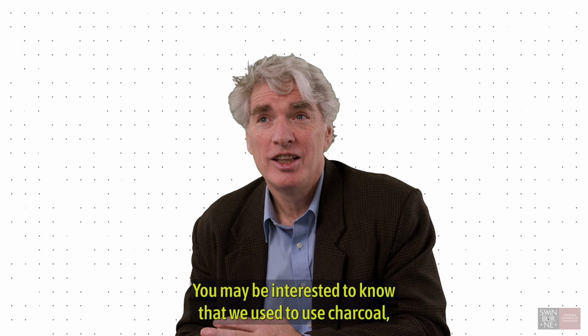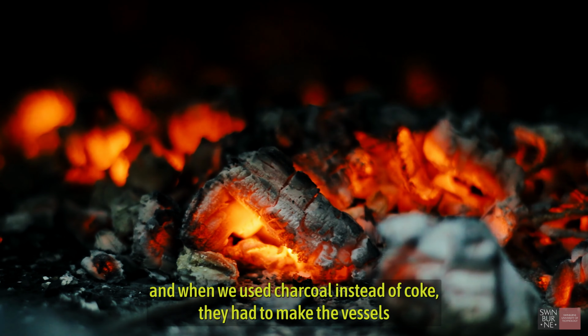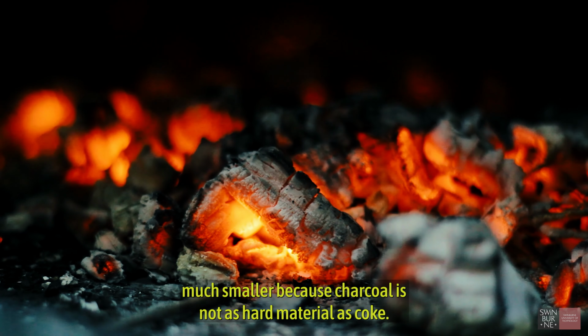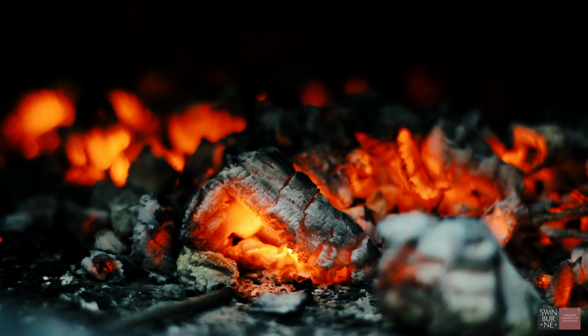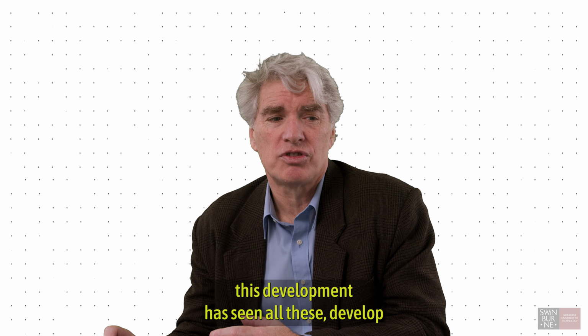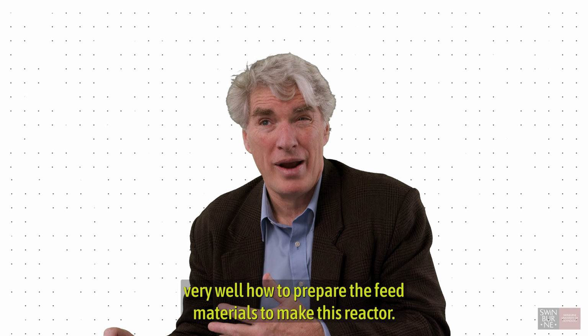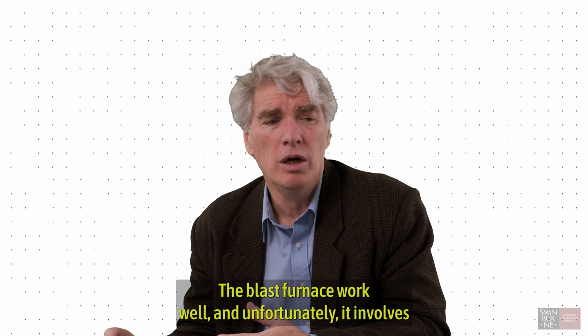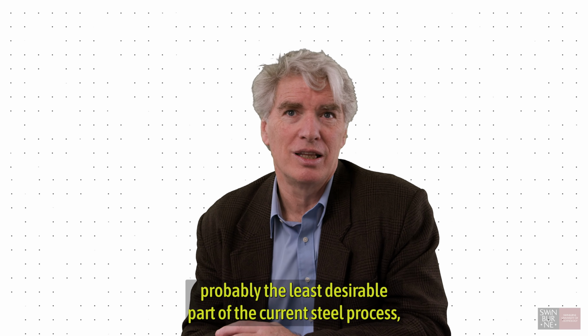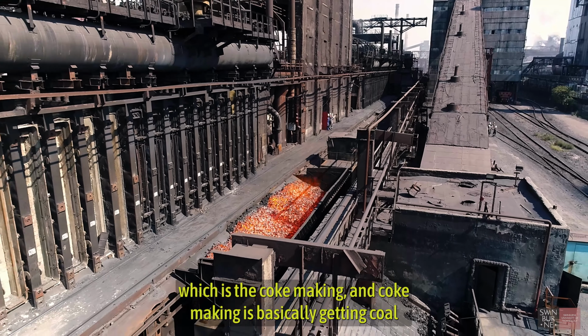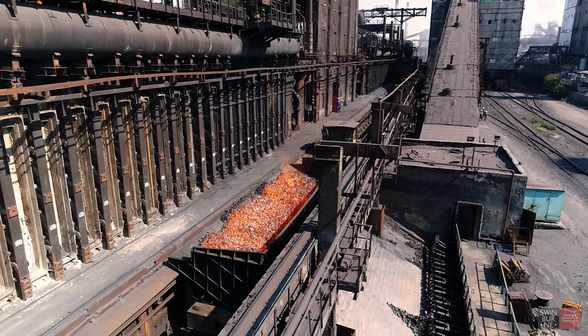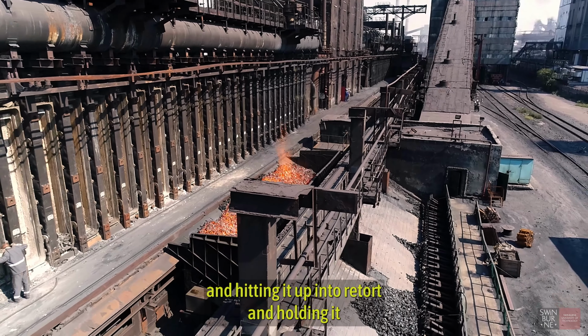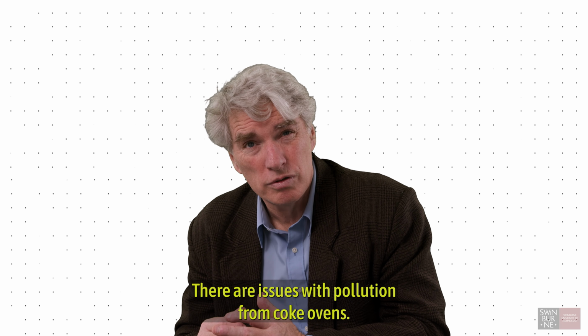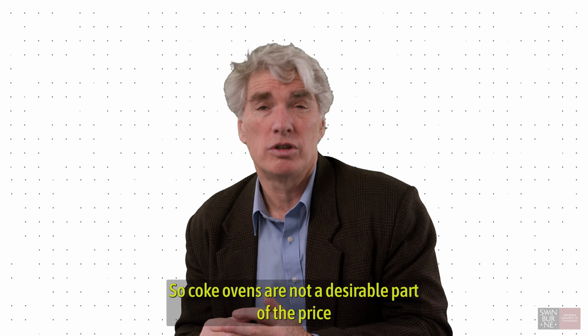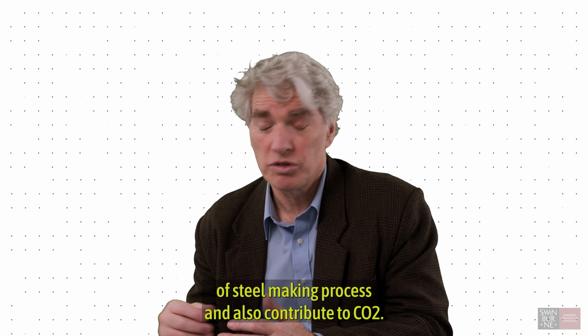You may be interested to know that we used to use charcoal, and when we used charcoal instead of coke, they had to make the vessels much smaller because charcoal is not as hard a material as coke. So this development has seen all these develop very well how to prepare the feed materials to make this blast furnace reactor work well. And unfortunately, it involves probably the least desirable part of the current steel process, which is the coke making. And coke making is basically getting coal and heating it up in a retort and holding it for up to 1,000 degrees for quite a few hours. And it creates a lot of volatiles. There are issues with pollution from coke ovens. So coke ovens are not a desirable part of the steelmaking process, and also contribute to the CO2.